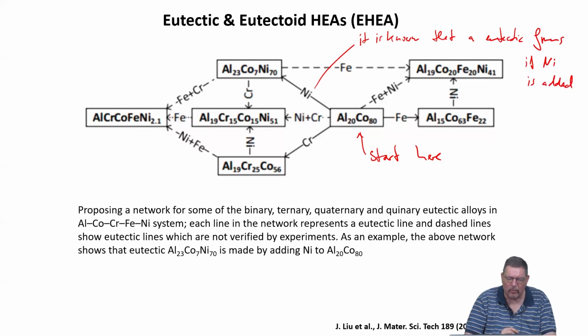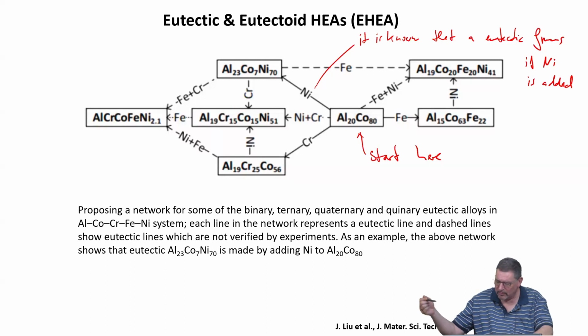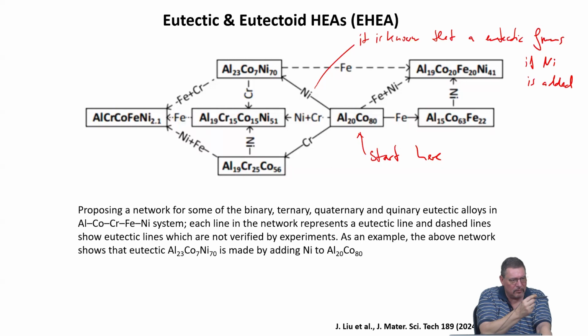Then you again know that iron and chromium with this, or if you would use chromium, you would get another eutectic. And this is why chromium and nickel have the same tendency for the formation of a eutectic, starting from the binary, and then iron is basically added without knowing it beforehand. So it means that you basically go from known eutectics, and then you add from binary to ternary constituents where you know that the eutectic is likely to form. Then you go to the quaternary, then you go to the quinternary. So it means it's like a network in that sense, that you go from eutectic to eutectic to eutectic, and you always increase the dimensionality of your alloy system. And this is, again, how people empirically look for and try to find compositions which are eutectic high entropy systems.